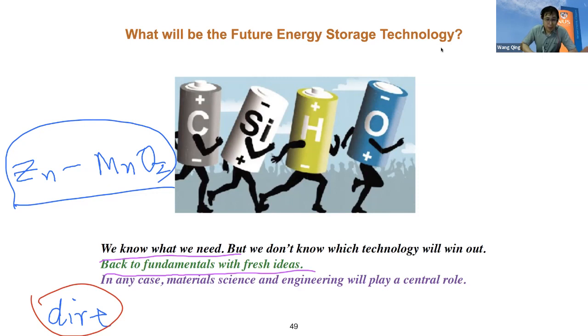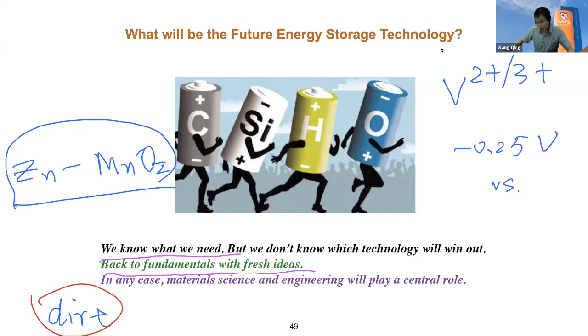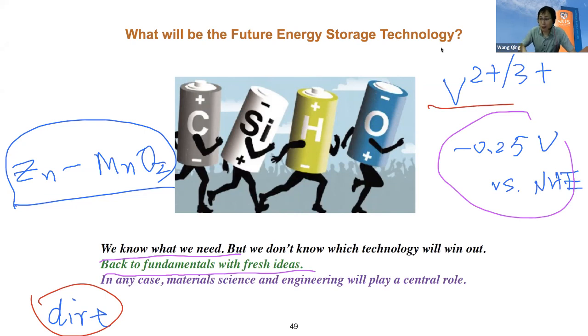The vanadium flow battery issue is mainly on the negative side, which is the reaction of vanadium. If you look at the potential, it's minus 0.25 volt versus NHE. We know the hydrogen formation is 0 volt, right? And this potential is already more negative than hydrogen formation. That means thermodynamically, when this redox couple gets reduced on the electrode, hydrogen will be formed already. Hydrogen becomes a safety hazard for use, because we don't want hydrogen to catch fire and cause an explosion, right? So we should try to get rid of hydrogen formation, for example by modifying the electrode, so they can suppress the hydrogen formation.